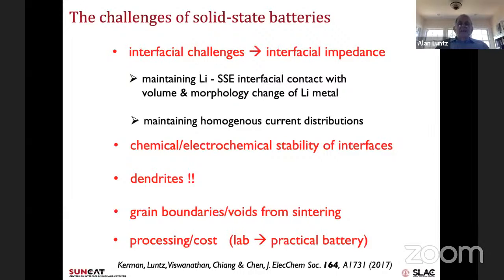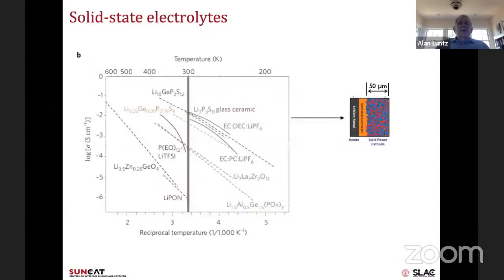Okay, so one of the things I didn't say is a challenge is lithium-ion conductivity, because it turns out that when you look at the conductivity, this is a log of the conductivity versus 1/T or T up here. These are conventional liquid electrolytes in batteries today, these curved lines. There are several electrolytes that have lithium-ion conductivities comparable to those of the liquid electrolyte, particularly these sulfides. Some of the oxides, particularly this one, and some of these others have conductivities that are roughly an order of magnitude lower, but they're still in a regime which is good enough to build a battery.